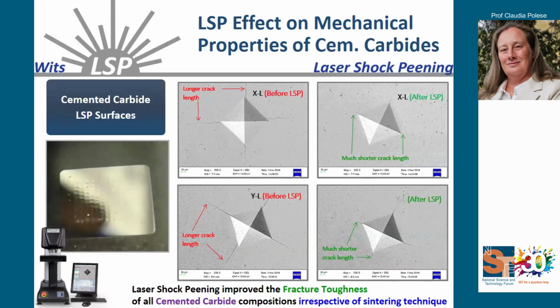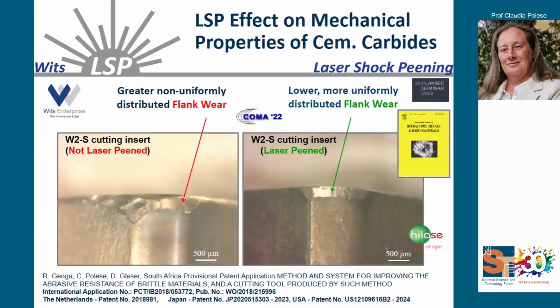Now here on cemented carbides, we honestly are not 100% sure how it actually works, but it works. So we actually saw that these cemented carbides that we are busy developing for another process are drastically improving the fracture toughness after we apply the laser shock peening on the surface. And also the wear, so obviously the cutting insert while it's cutting is lasting much longer.